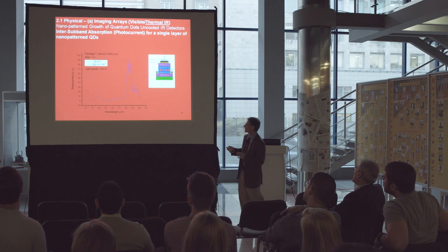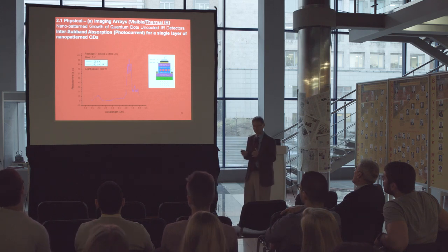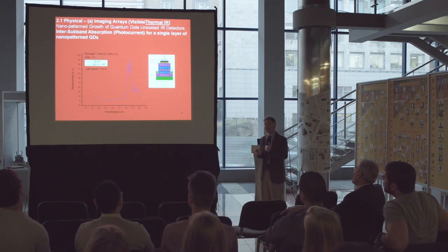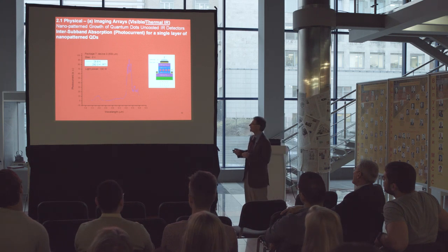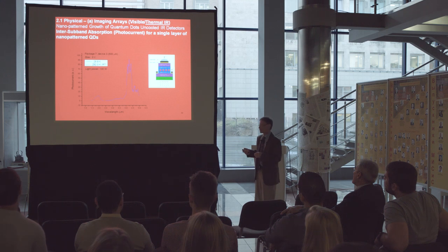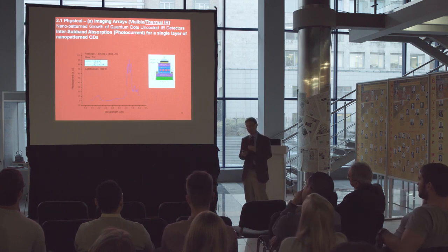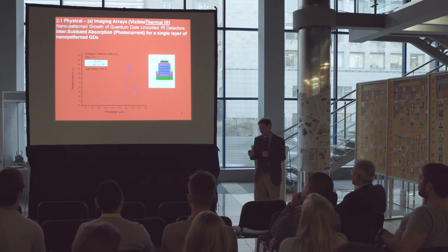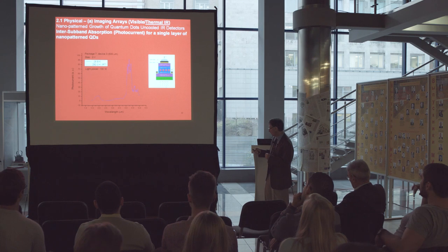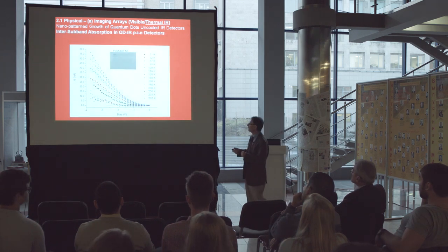And this is low temperature, but when the size gets small enough, and you think about all the phonon issues, you actually can, in very small size objects, keep these things stable to high temperature, and we in fact did. We got them stable to liquid nitrogen with incredibly high sensitivity. And by changing the dimensions, you change the energy level structure, so we can tune where we want the spectral response.